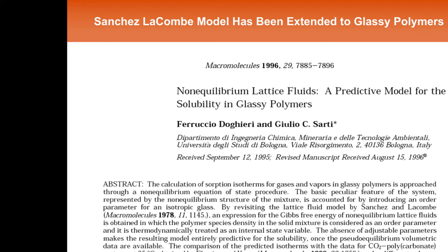And that was the point in the previous lecture where we compared the CH prime value of carbon dioxide and polyethylene terephthalate as a function of temperature from the Paul and Koros work, and saw that CH prime went down almost directly in proportion to how the excess volume went down as temperature went up towards the glass transition temperature. And so underpinning that is that CH prime is proportional to the effective size of the penetrant in those Langmuir sites.